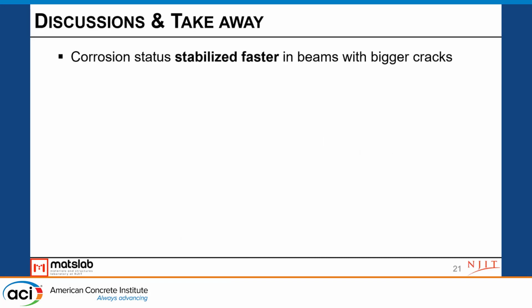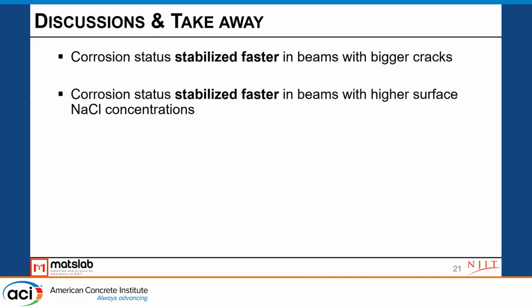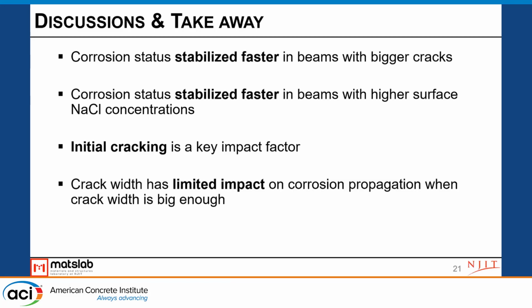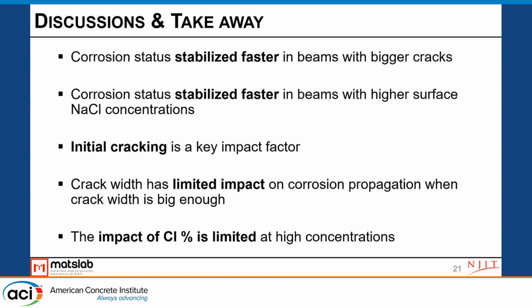So here are some takeaways from the simulation results. Corrosion started to stabilize at some point, and it stabilized faster when we have a bigger crack width, and also when we have higher surface chloride concentrations. But the key factor here is the initial cracking itself, not the crack width. Crack width has a limited impact on the corrosion propagation, which is kind of counterintuitive. And also the impact from the surface chloride concentration is limited, especially at high surface concentrations.